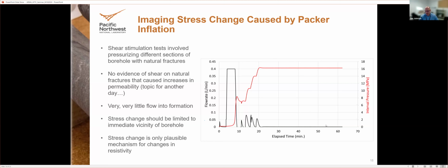As you can see, there's no real change here, and the flow rate into the zone was very, very small. But what we did do is exert pressure on the borehole walls and exert compressive stress on the rock around the boreholes, and that was all monitored with the ERT system. And that is what we're seeing here.